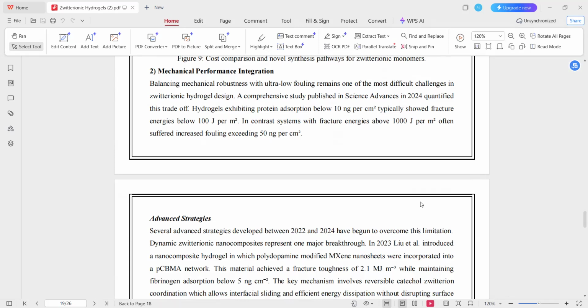Mechanical performance integration. The second challenge is balancing mechanical robustness with ultra low fouling behavior. A comprehensive study published in Science Advances in 2024 quantitatively demonstrated this trade off. Hydrogels with protein adsorption below 10 nanograms per square centimeter typically showed low fracture energies, often below 100 joules per square meter.